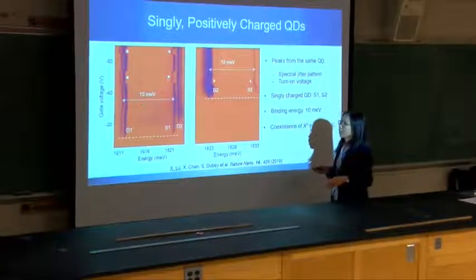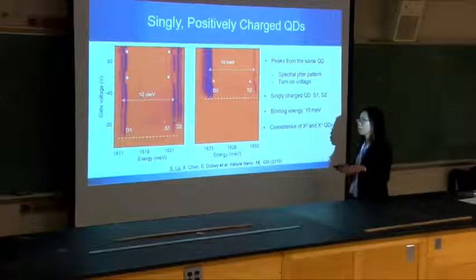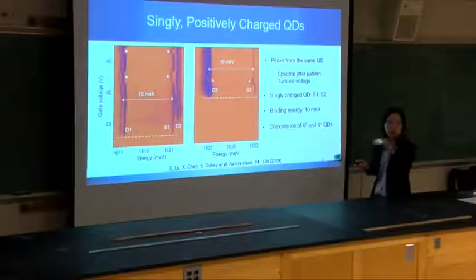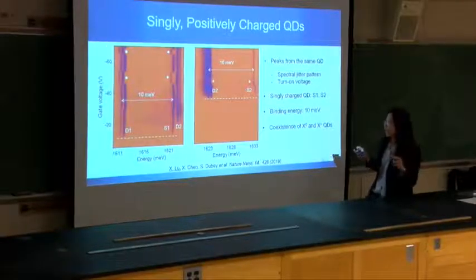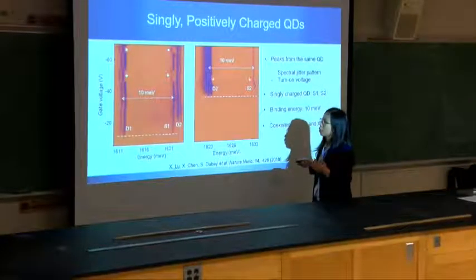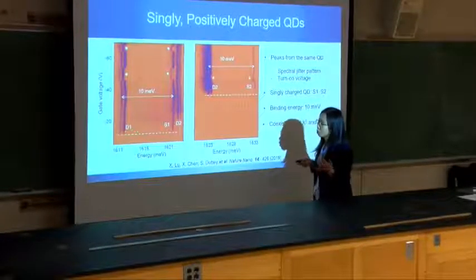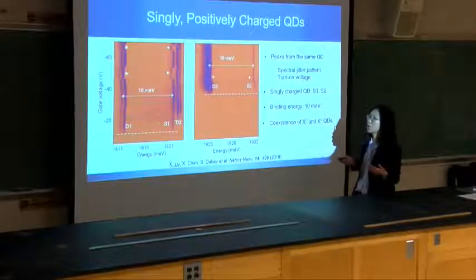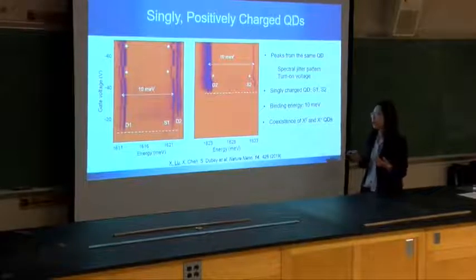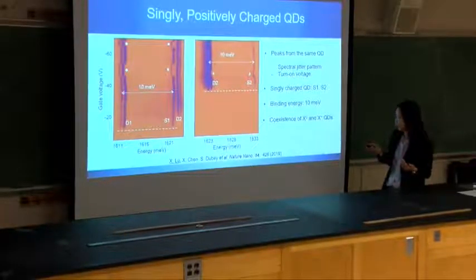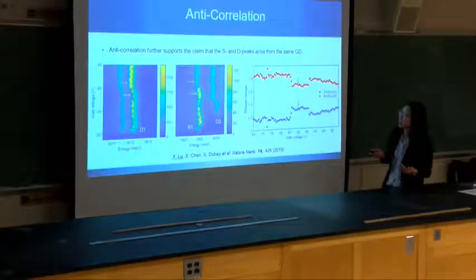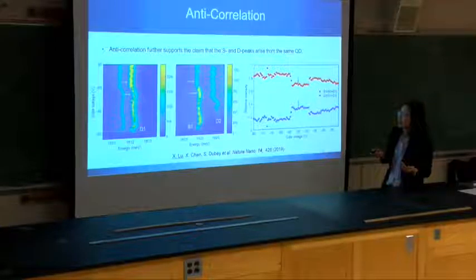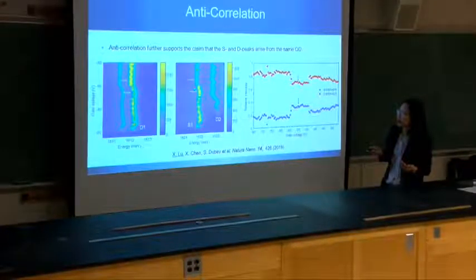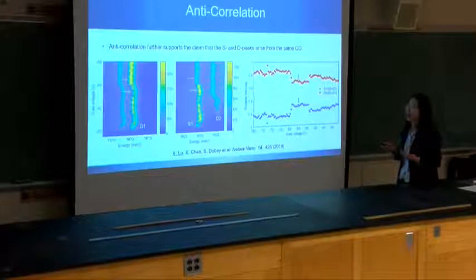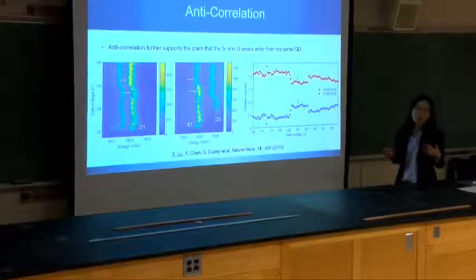And we see the coexistence of neutral and charged quantum dots, which means that the charge loading in this FET device is not perfect. The coexistence means that the neutral potential dot captures or releases an extra hole on a much faster time scale compared to the integration time of the spectrum. But occasionally we do see anti-correlation, as you can see here, where the neutral dots are weaker and the charged dots are stronger, and here the charged is weaker and the neutral stronger. This further supports our assignment that the S peak and D peaks are related to one potential trap.